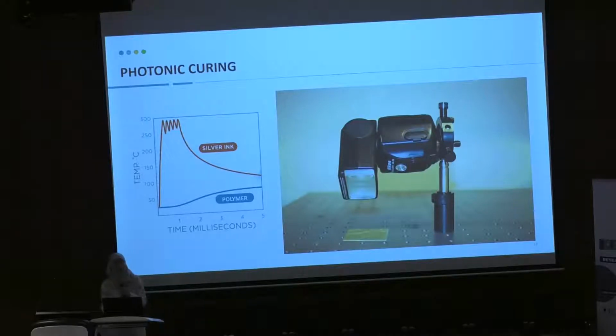Also, since we are using biodegradable materials, they have a low melting temperature. So when we want to cure the printed patterns, we use a unique method called photonic curing. Simply, we use a camera flashlight to hit a pulse of light on the printed patterns. This will increase the temperature of the printed inks instantly and within a few milliseconds without degrading the polymer.